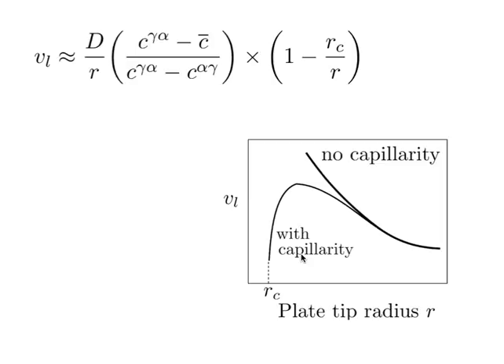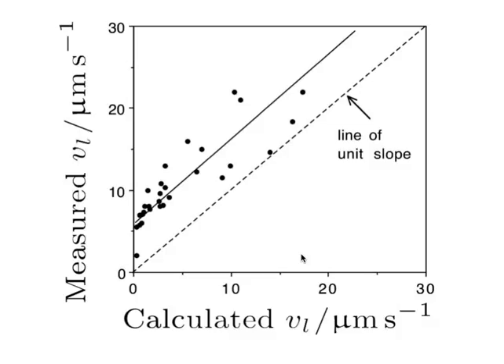Picking the tip radius which gives the maximum velocity, the only way to verify this assumption is by comparison against experimental data. Here are some measurements of the lengthening rate versus that calculated, and you can see that we get a velocity somewhat greater than the maximum value — but remember we are assuming a nice neat parabolic cylinder shape. Getting it wrong by 5 micrometres per second is not a big deal, and you can see that for a whole variety of different alloys the growth rate follows that prediction, showing good agreement between experiment and theory.